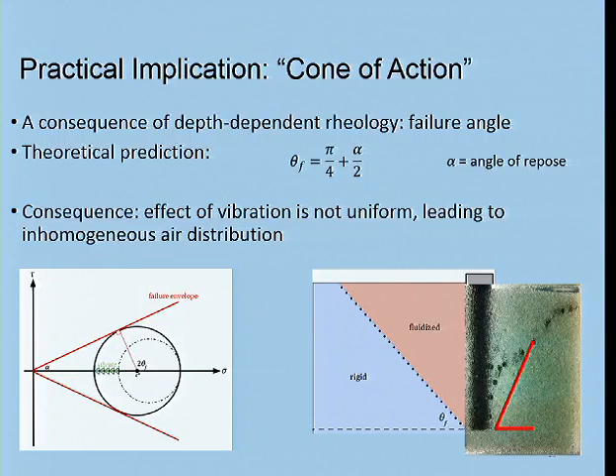But it didn't last forever. There's sort of a dissipation zone. The other thing you see is that not all these balls were treated the same. This vibration rod is moving back and forth, but the ones close were more dramatically affected. And this led us to coin this phrase of cone of action. Now, if you're a concrete technology person, you would recognize the term radius of action. You put a vibration probe into concrete and you see a radius of action that gets fluidized. And we recognized pretty soon that this was a misnomer of sorts. We were seeing it as a radius of action only because we're looking only at the surface. If we were able to look all the way down, we would recognize that was not a radius, a cylinder of action, but in fact was more of a cone of action. And it changes pretty significantly how we think about consolidation and the propagation of vibration through these systems.